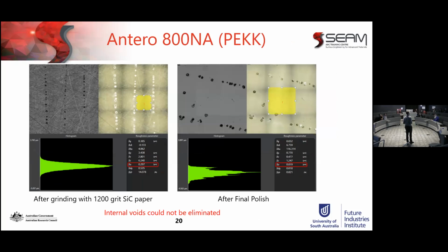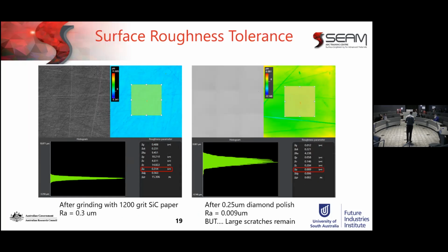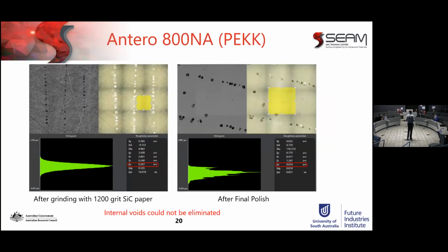Like I said, we had to fuse the plastics together. That plastic there fused really nicely. This one here didn't fuse completely. You can still see the porosities running down. So no matter how much we ground, how much we polished, we kept exposing these porosities. So this plastic we could get to fit wasn't fit for purpose.